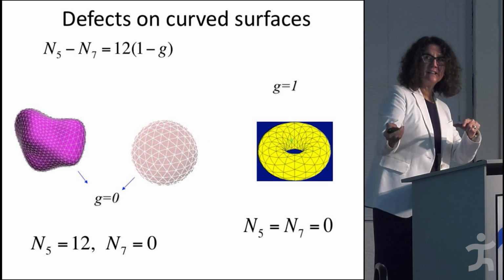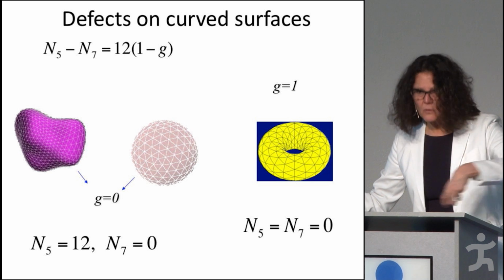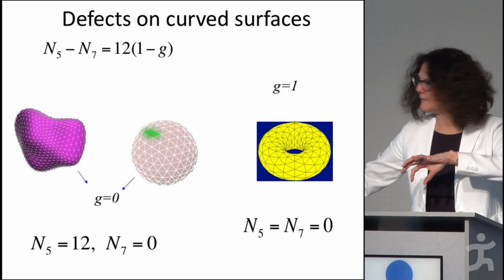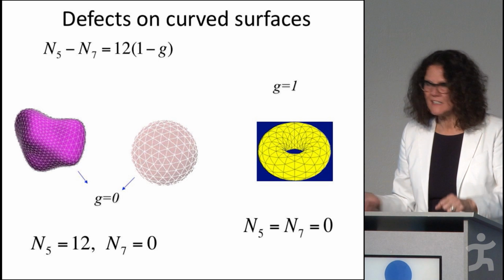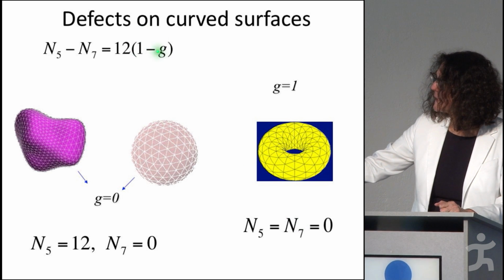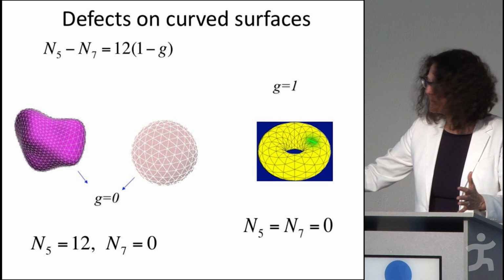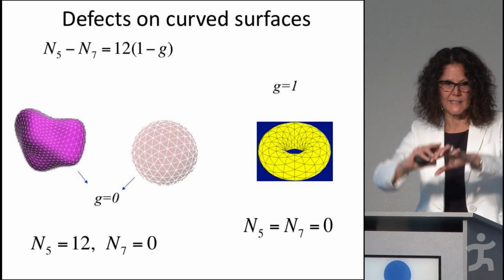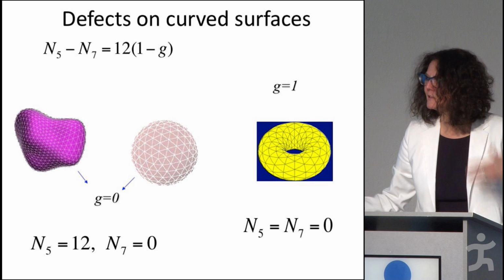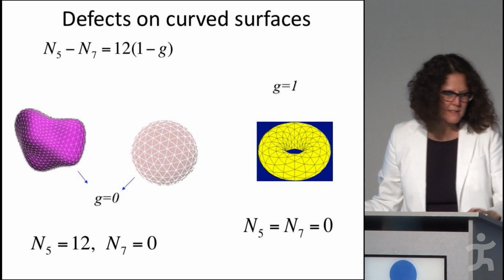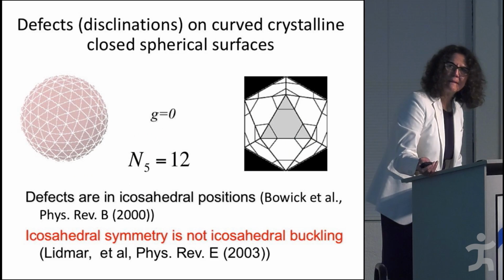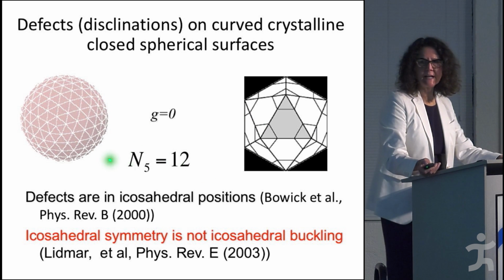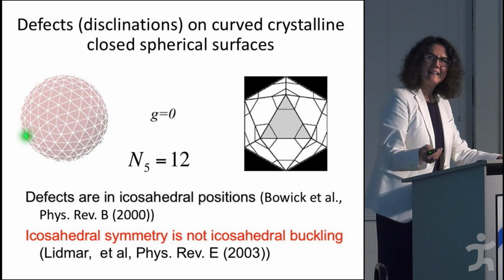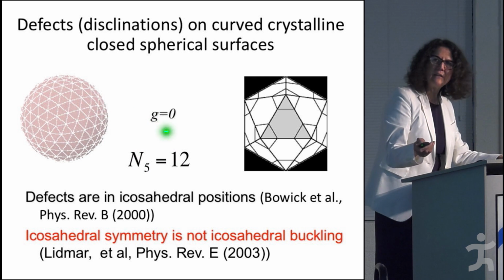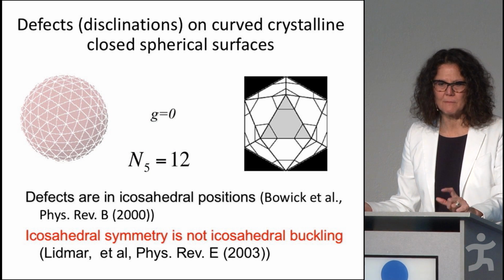If it was something that has genus 1, which means 1 handle, like a toroid, then it doesn't need defects because 1 minus 1 is 0. So you can actually take a tube and fold it and cover it and it doesn't spike, right? You don't need the defects that are so dangerous. And this is something we've known from Caspar and Klug for viruses, that the spherical viruses have icosahedral symmetry. And the reason for that is because these 12 defects hate each other.